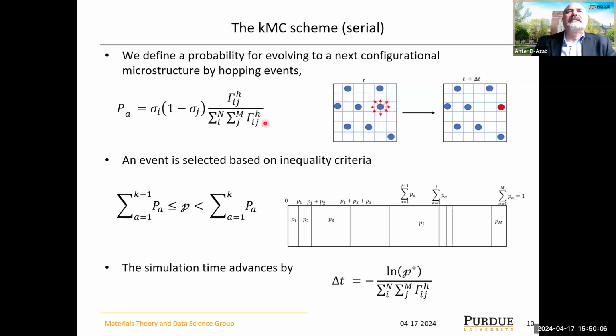The probability of hopping is given by this rate normalized to the total rate for a particular process, and these are occupancy numbers on the surface. It is executed through a random number, and the probabilities of an event given that events have not taken place, so it's just schematic here. So that probability gives us the time step, and the ability to compute time based on hopping rate is what gives the name to the Monte Carlo scheme here, kinetic Monte Carlo.